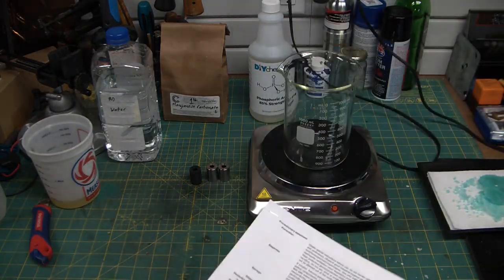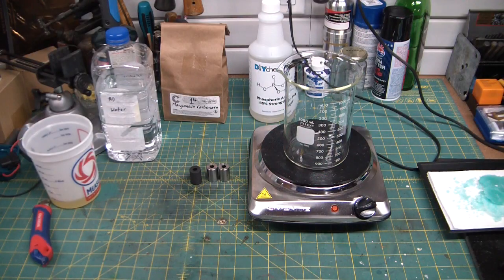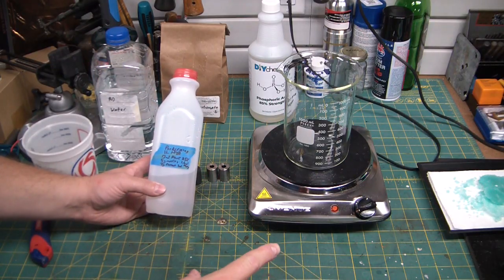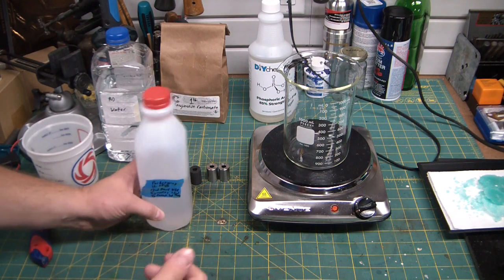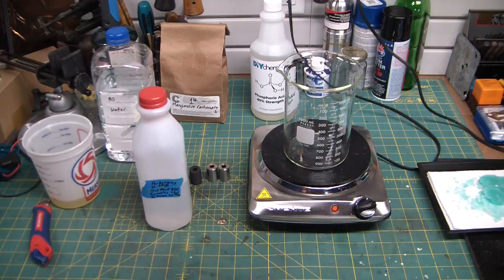I tend to be rather messy and don't want cancer. So what I eventually settled on for the homemade solution is for every liter of distilled water, or in this case I'm just using RO water, is 12 milliliters of 85% phosphoric acid.